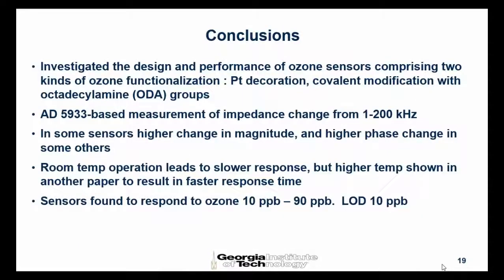So in summary, we have presented the initial results for platinum decorated and covalently modified ODA group functionalized single-wall carbon nanotube-based sensors. We used an Analog Devices chip for impedance measurement on board, or eventually on chip, between 1 and 200 kilohertz. We found that some sensors respond well in magnitude and the others respond well in phase. So some kind of array would be a solution in the future.